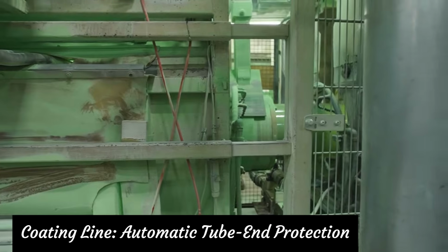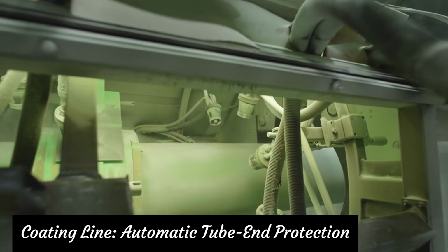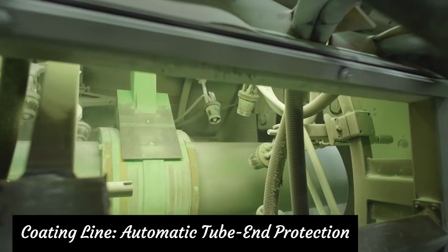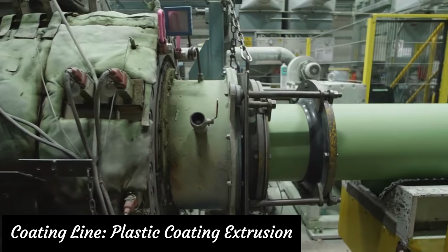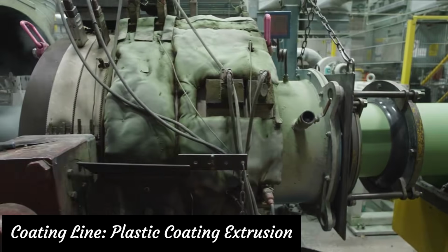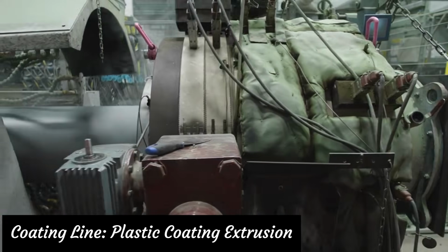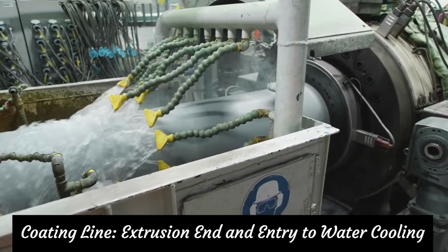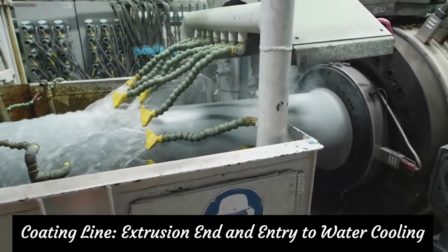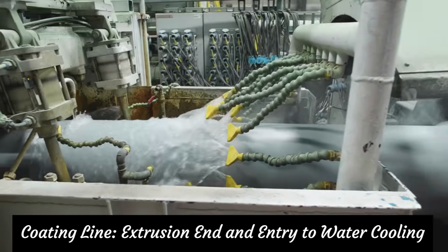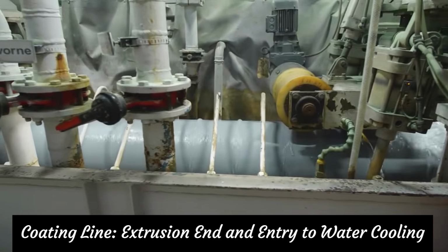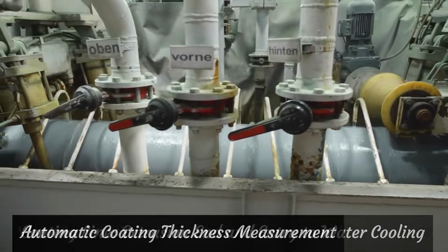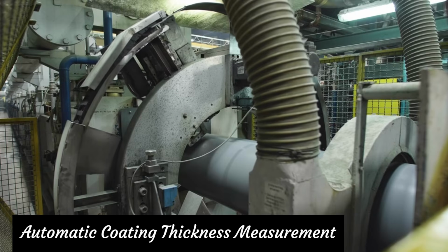A primer layer is applied using powder coating to improve corrosion resistance. A plastic layer is extruded over the tube surface. This creates a uniform, protective coating. After coating, the tubes move into the cooling zone. Controlled water sprays cool the coated tubes to stabilize the coating thickness. Sensors verify the coating thickness in real time.